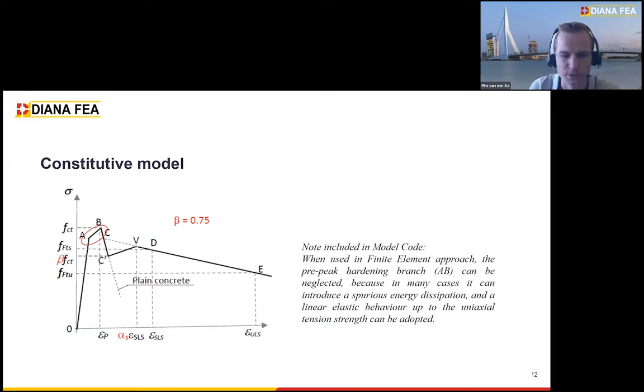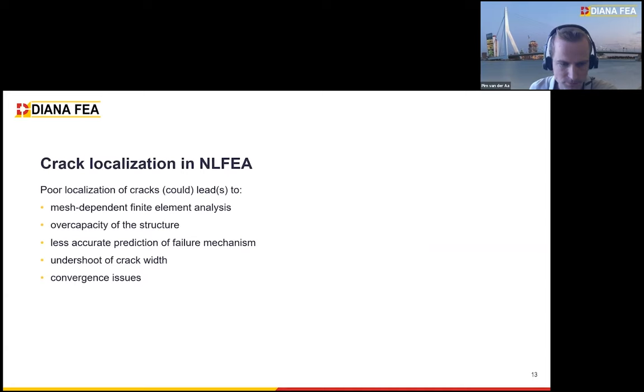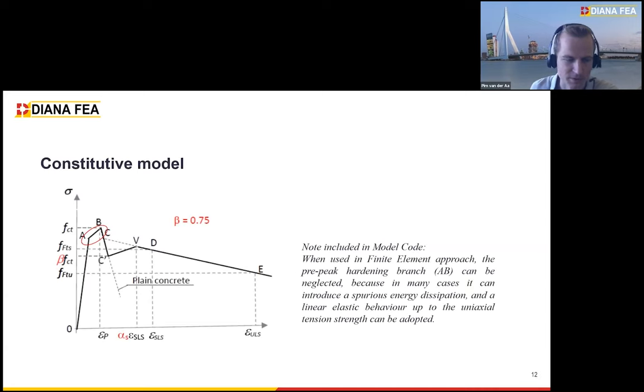Next up, we come to the second part, which is about crack localization. Maybe good to mention also that with the point C prime, not only can a more realistic stress strain diagram be introduced, but it can also improve the crack localization. That's also an extra benefit of this stress strain relationship.